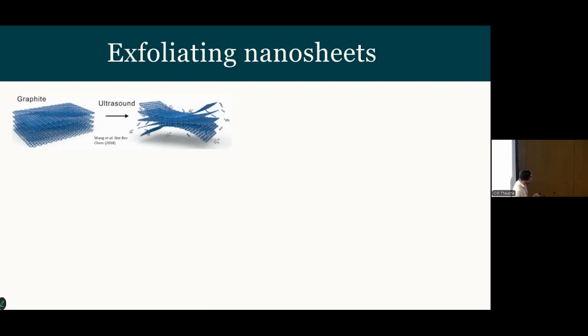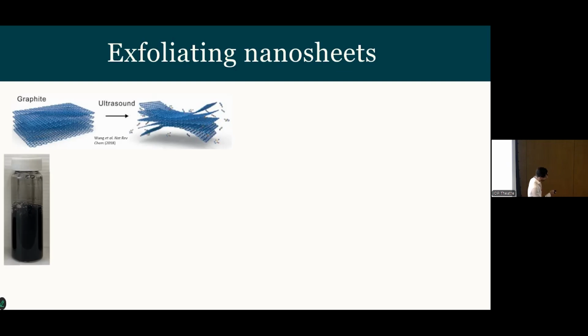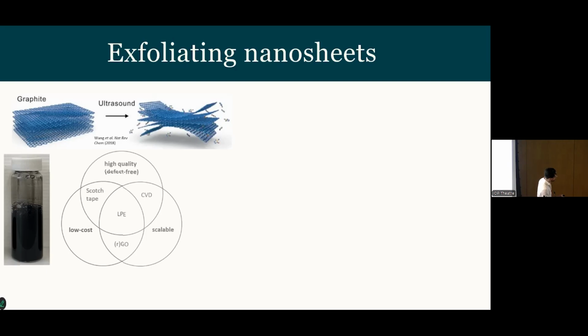By choosing either surfactant solutions, so amphiphiles, soap molecules, or appropriate solvents, we can disperse these nanosheets from bulk crystals into dispersions which look something like an ink. We have lots of nanosheets floating around, relatively stable, not fully colloidally stable, but kinetically stabilized in these dispersions, and we can then do lots of things with these. This crude simplified Venn diagram is using this technique, which is known as liquid phase exfoliation, LPE. Just to put into some context, we believe we produce defect-free nanosheets of relatively high electronic quality, and hopefully you'll see that from some of the results later.